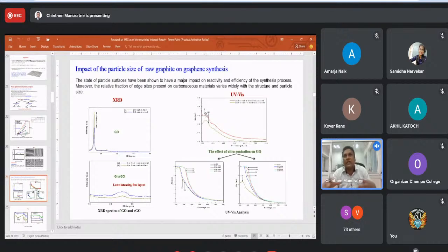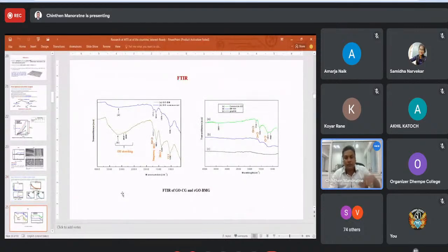Because their activation sites are now increased. When you reduce the particle size, the reaction sites increase and the reaction takes place very efficiently. That is why you get the high absorption. And also, if you take this XRD for reduced graphite oxide or graphene, you can see a very low intensity peak that represents the graphene present, and it is more reduced in the ball mill graphite. So like that, you can see a clear difference between these products based on the particle size.